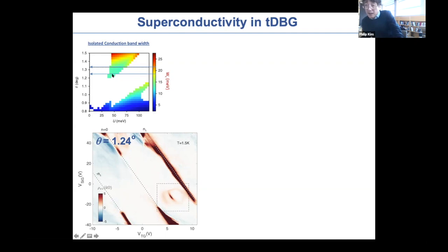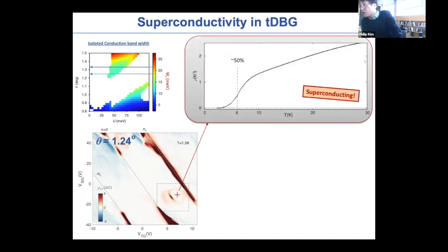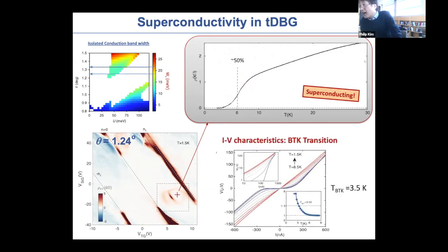And with this even narrower bandwidth system, when you dope it, we start to see that the system shows superconducting-like transitions, where the finite resistance drops quite rapidly and gets into zero resistance. And once you get into this zero resistance state, we measure the IV, and the IV shows a strong nonlinear behavior. This nonlinear behavior, with the temperature and magnetic field dependence, clearly follows BTK type transition behavior, and is strongly suggestive that this might be related to the 2D superconductivity we measured in this type of system. So that is another exciting thing.